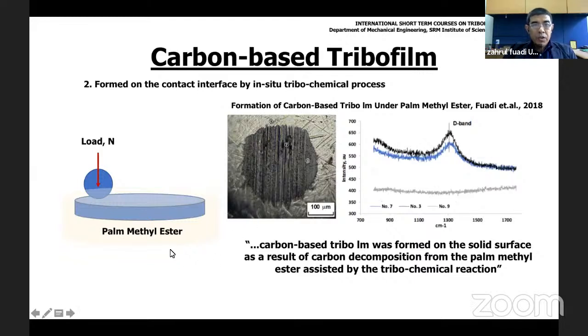And this one also shows that by using bio oil, here we use palm methyl ester, which is derived from crude palm oil, after the friction we can find some peaks here in the D band, which shows that this is a carbon-based tribofilm. This carbon-based tribofilm was formed on the solid surface as a result of carbon decomposition from the palm methyl ester assisted by tribochemical process.